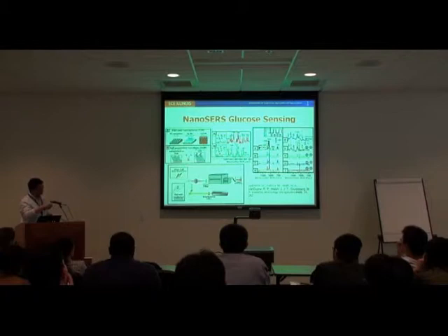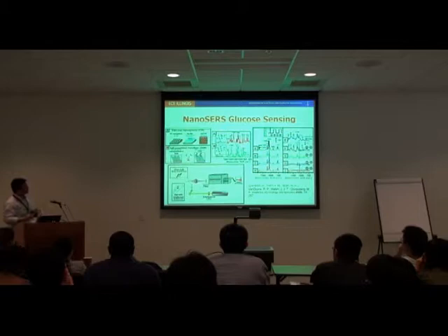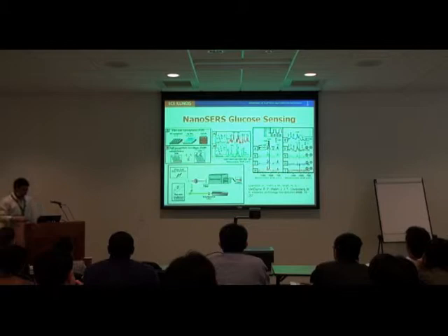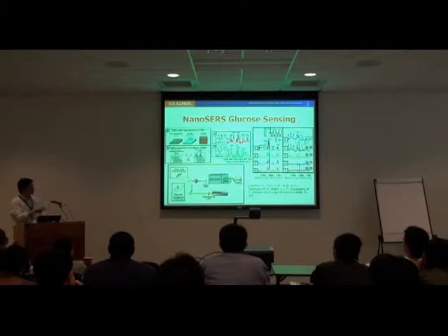The way they did it, because they're chemists, is they assemble nanospheres into an array and then deposit a silver film on top of that to form a substrate they call silver on nanostructure surface. Then they assemble different monolayer molecules onto the surface and create a pocket for the glucose molecules. So they can compare the SERS signals of those molecules before the glucose molecule attaches and after it gets into the pocket. That's exactly what they do.